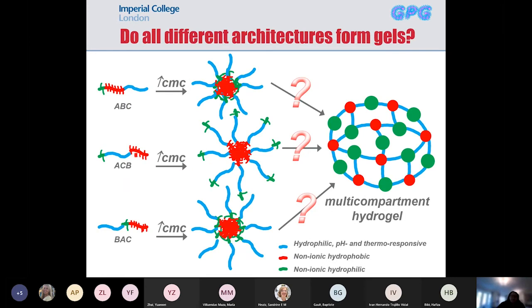So we were the first group to investigate how the architecture of ABC triblock polymers would affect the thermogelation. So we know that they're going to make micelles, and we know that the micelle of this one will be smaller in size, and that's confirmed experimentally. Because the hydrophobic block is in the middle, then essentially if your thermoresponsive block is longer, like it is here for the one in blue, we know that that will be the length of the corona.